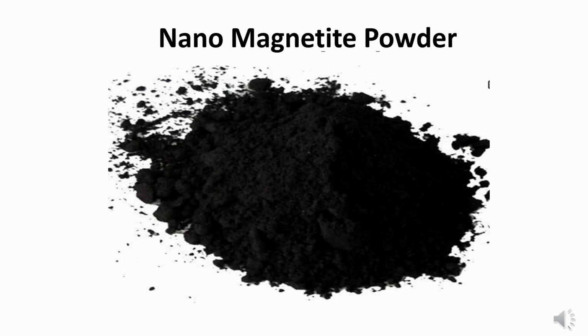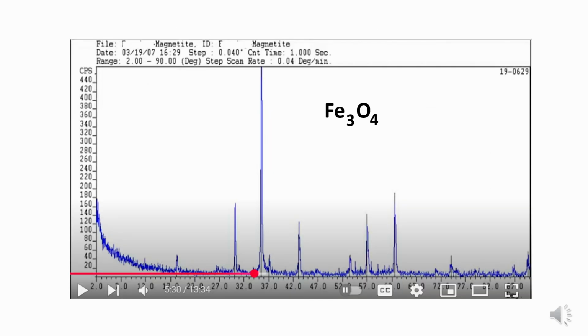Because of my curiosity, I decided to determine the purity of the powder and size of the particles. Using X-ray diffraction, the black powder was shown to be very pure magnetite, Fe3O4. Using a scanning electron microscope, the magnetite particles exhibit an octahedral crystal shape, with sizes ranging from 20 to 50 nanometers. This was a surprising observation.